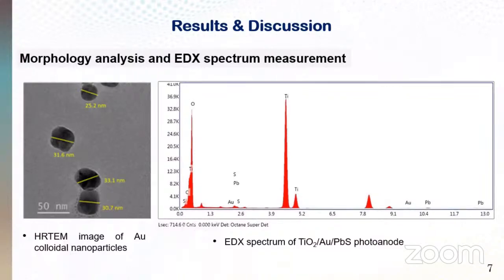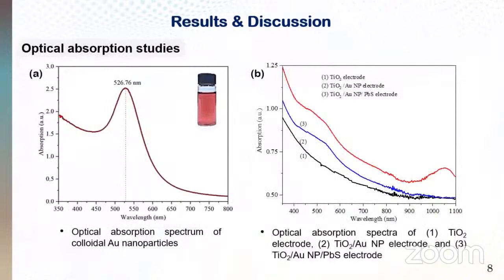the TiO2 electrode. Figure A shows the optical absorption spectrum of plasmonic gold nanoparticles. It shows a broad absorption in the visible region, which peaks around 527 nanometers. From this absorption maximum, the average particle size of the gold nanoparticles has been approximately estimated by comparing with the published articles, which is in the range of 25 to 35 nanometers. This result was confirmed with TEM images.